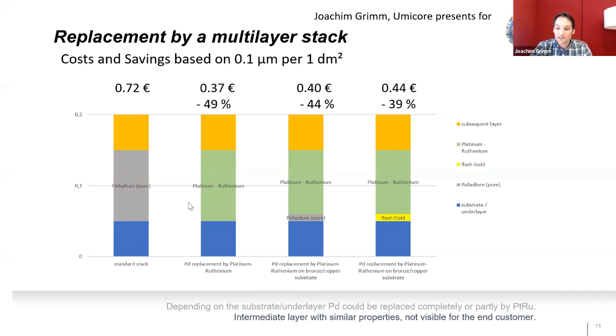So the easiest way in that case is we go as well for an intermediate layer, giving us corrosion and diffusion protection, so nothing can migrate from the substrate material to the top layer. So the Platinum-Ruthenium is perfect for this as well. It gives the same properties. In hardness, it's even harder, and corrosion protection is there. And at least like in the other level 3 I told you, if you do a plating on top, nobody can see the Platinum-Ruthenium in between. And if it's changed from palladium to Platinum-Ruthenium, it's totally exchangeable, whichever part you do.